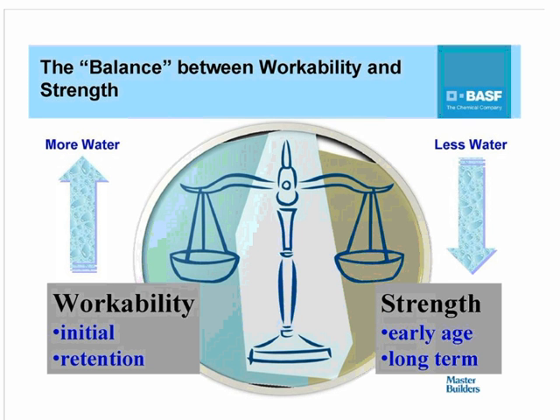So before the advent of chemical admixtures, one way of increasing workability was to add more water or to add more cement to the mix, and by so doing, also increase the water content accordingly. On the other hand, from a strength perspective, the concrete producer is interested in using less water because reducing the water content increases the compressive strength, both early age and long term. So it would appear as if we have a conflict where on one hand, the contractor would like to have more water in the mix to improve the workability, and on the other hand, the concrete producer would like to have less water in order to improve the strength of the concrete.